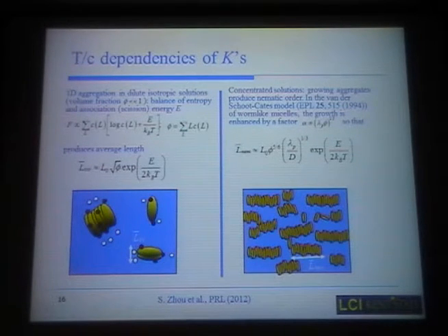Here again, it's the balance of entropy that would like the monomers, the little chromonic molecules, to be dispersed in space freely, and the sticking energy, this non-covalent bonding, that hydrophobic bonding, if you wish, that keeps them facing each other within the columns, that sets the length or the aggregation number in the system.